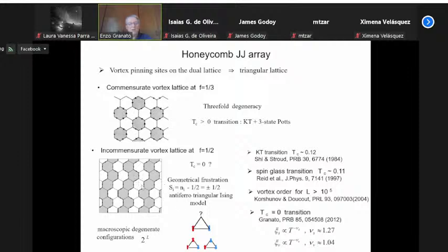Then, since they are located at the center of the plaquettes, this is actually similar to an antiferromagnetic Ising model on a triangular lattice, which has frustration. If you have one spin up, the next spin can be down because the interaction is antiferromagnetic. But then the third one cannot be satisfied with both neighbors, because if you satisfy one, you cannot satisfy the other. As a result, there is a degenerate ground state, similar to the ground state generated by that model, although the models are different. But this suggests that the critical temperature for this case is also zero.